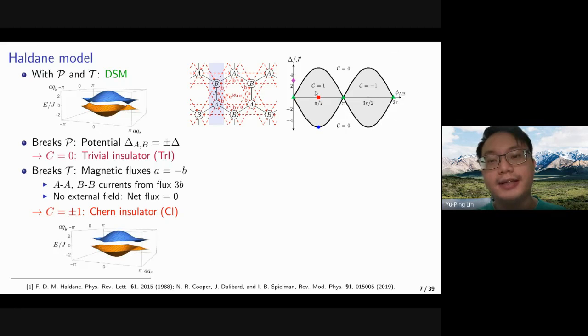So we can now look at the phase diagram here. First, if we preserve both inversion and time reversal symmetries, which correspond to 0 on-site potential and also some real condition for the phase, that is 0 or pi, we're having the Dirac semimetal. And this Dirac semimetal will serve as a critical point between the Chern and trivial insulators. If we introduce the on-site potential, it will go into a trivial insulator. If we introduce a complex phase which corresponds to the current, it will go into a Chern insulator.